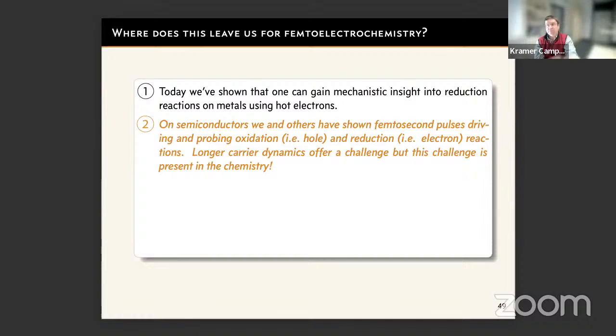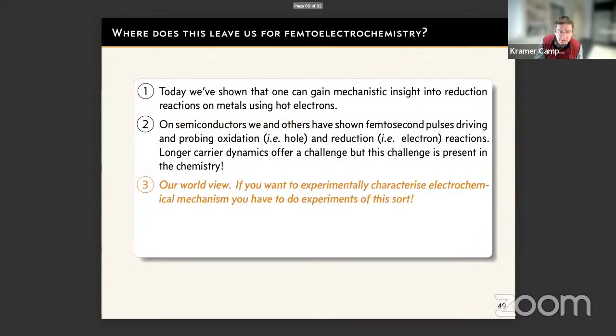On semiconductors, we work on this, and a variety of others have shown that you can employ femtosecond optical excitations to drive oxidation chemistry, to create holes at the interface that can accept electrons from solution, or reduction chemistry, to create electrons that can be donated into solution. The challenge here is, of course, that many of these carrier dynamics in semiconductors are quite long-lived compared to metals, so you can have relaxation processes within the semiconductor that are unrelated to electron transfer to solution that happen on the same timescales. But of course, there are ways to deal with these problems.